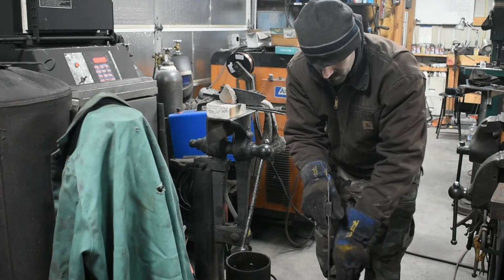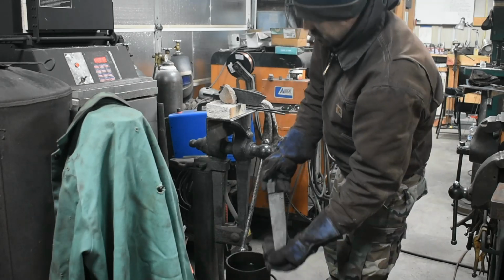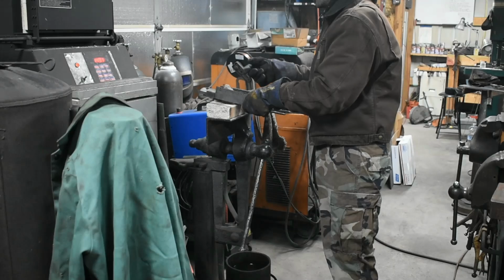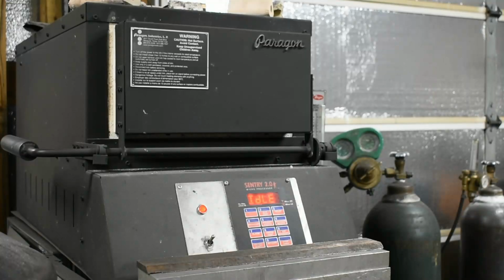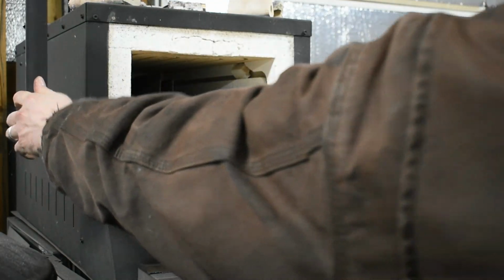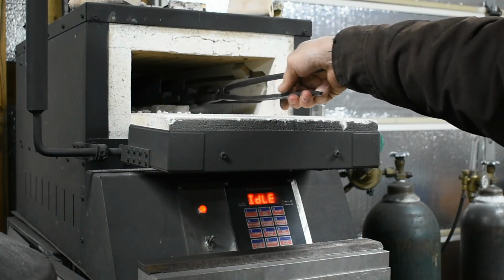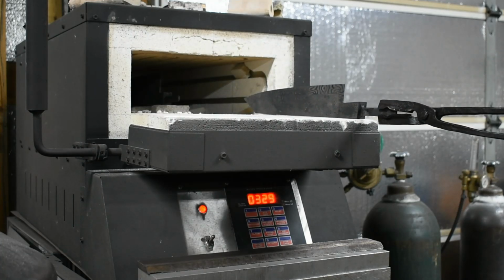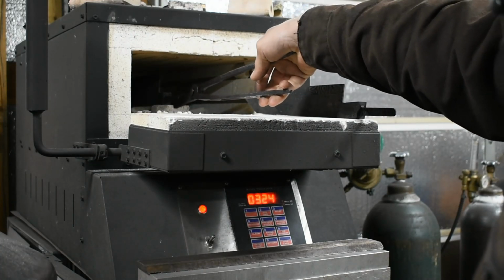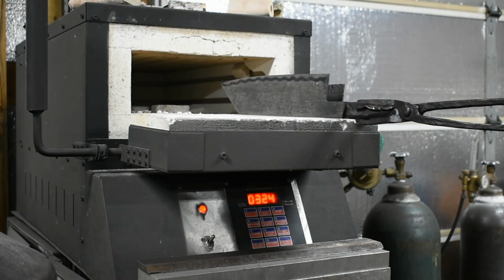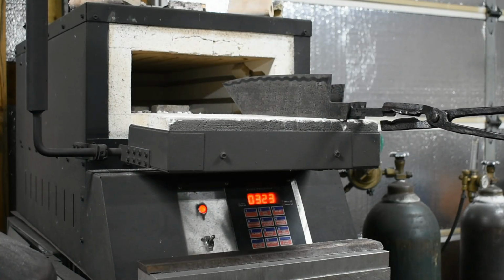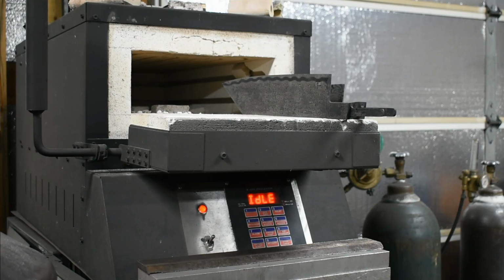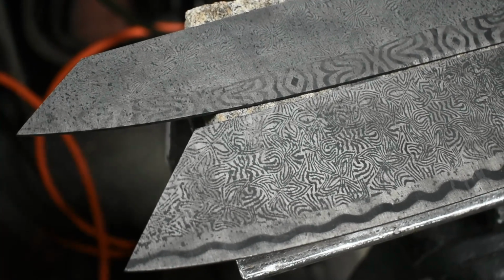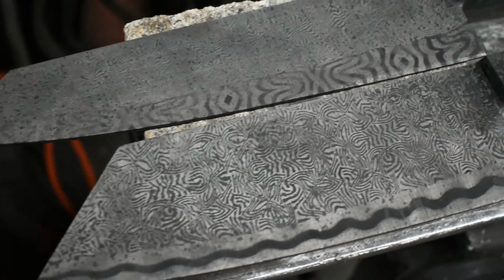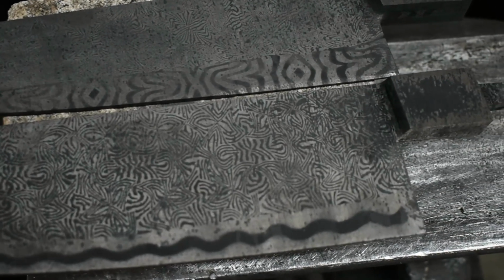Both of these blades did just fine though, barely needed anything. And so now I'll let them cool. They went into the house oven for a snap temper. And then I put them in the shop oven here again for their finish temper cycles at 330 degrees. 2 cycles of 330 degrees. So they're done tempering. I have a quick flyby of the pattern poking through the scale here. I always have fun seeing that.